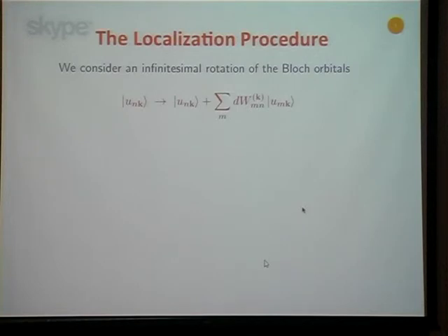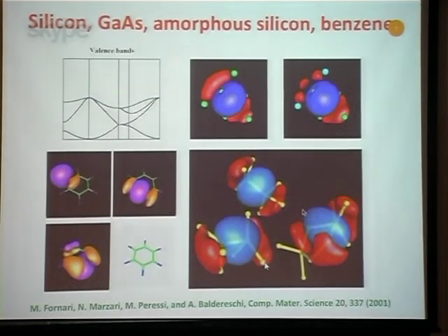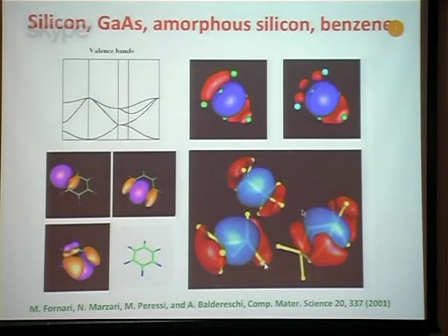You typically would do ab-initio molecular dynamics at high temperature, where silicon is liquid, then cool it down, but slowly enough, and it's a very difficult problem how to get a meaningful structure, a very long simulation in which you melt the silicon and then you cool it down slowly.